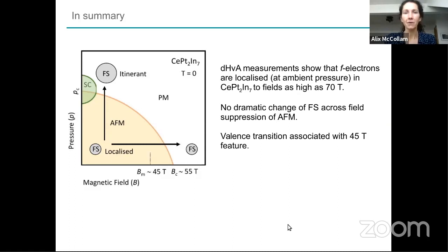Yeah, I guess the answer is no at the moment. The cousins of this material are the 115s that we know about at the moment, and they're just as inaccessible in a way. One thing that you can do, so with cerium iridium indium 5, for example, it's superconducting at ambient pressure, but if you dope with cadmium, you push it into the antiferromagnetic state. So with a small level of cadmium doping in cerium iridium indium 5, you get to a stage where you have a very weak antiferromagnetism that you can access or you can suppress with a very small pressure or a very small field. So it would put you in this corner of this phase diagram.